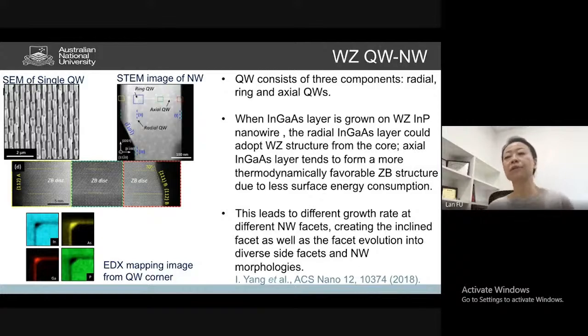So what's the reason? Of course, we've done a lot of TEM analysis and understanding. I'm not going to go into detail, because this nanowire formation is very complex. We need to think about the thermodynamic process, and the surface energy plays a very important role, because nanowires have multiple facets. So the surface energies for the growth are very different. Thereby, that leads to this non-uniform growth at different surfaces when we introduce indium gallium arsenide, and that introduces all this very complex morphology evolution. So that's what we've seen.